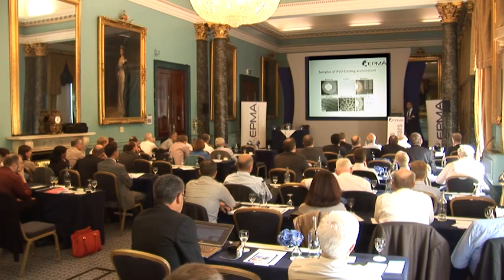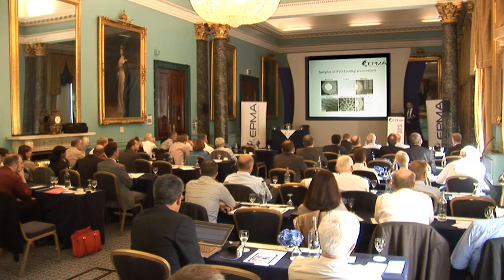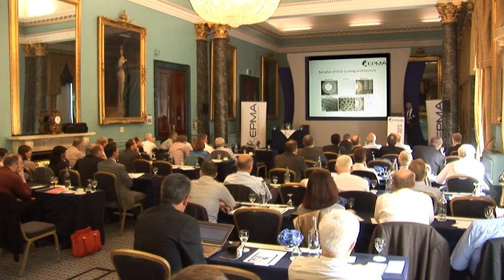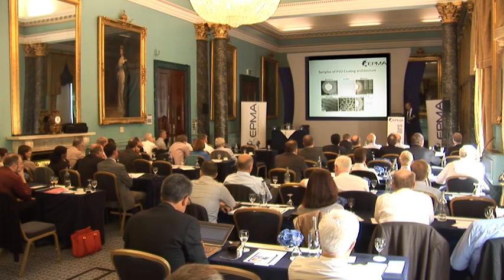But with the advent of PVD, which gives you a very sharp cutting edge, we have now moved away from the P grade of cemented carbide for cutting tools to the straight tungsten carbide cobalt grades with grain sizes of tungsten carbide of 0.8 microns. So 0.8 microns gives you also a sharper cutting edge. That means cutting forces are lower, you can run at higher cutting speeds. So these coatings have also given an added advantage of moving to much simpler substrate metallurgy.